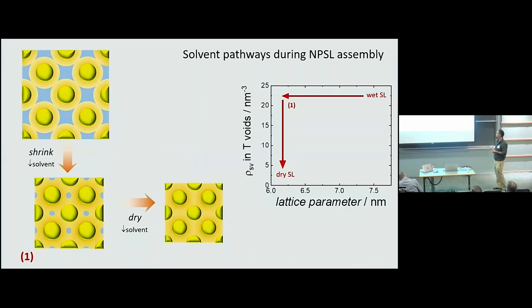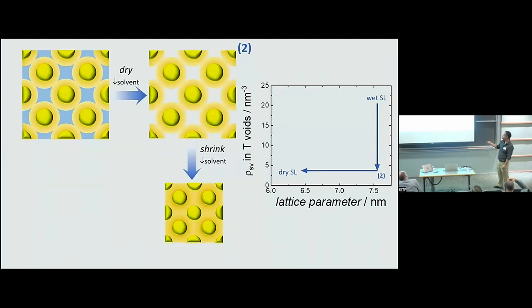So let's say we plot the density of the solvent in the voids. In this case, I picked some particular tetrahedral voids in the BCC superlattice as a function of the lattice parameter. So this pathway will involve first compressing the superlattice, but keeping the density of the solvent more or less fixed. And then at the end, we just dry the superlattice and the density of the solvent will go down. There is another pathway you can imagine that's actually the opposite one. So you first dry the solvent in the voids, and then you collapse the superlattice. And of course, probably the reality is something in between. But we wanted to ask the question, which one is better to describe the system? And this one, of course, will be the opposite, right? So you first dry, and then you collapse.